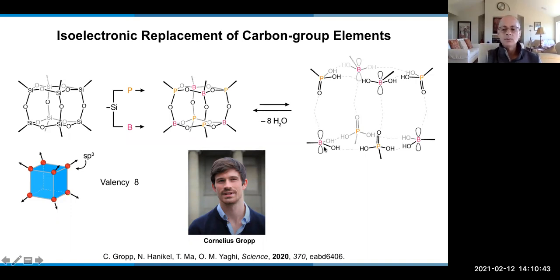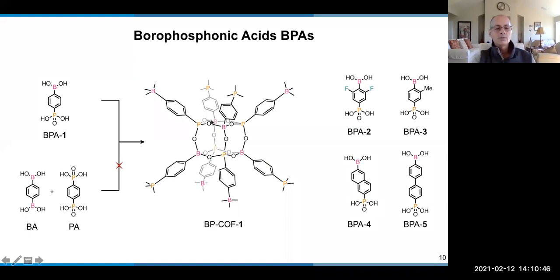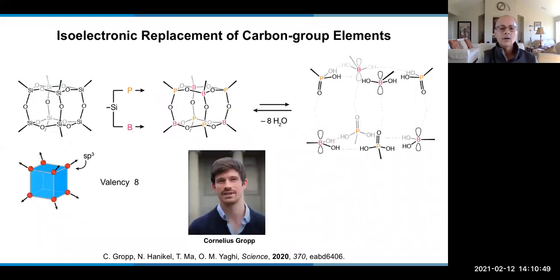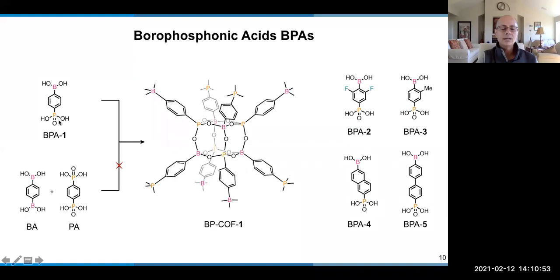So we thought this would work, and indeed, a great postdoc in my group, Cornelius Gropp, actually this was his idea entirely. First, we tried copolymerizing the diboronic acid and the diphosphonate, but that didn't work. What worked is that you make a molecule that contains the boron and the phosphorus. And because these are complementary, they come together into the cubic form. Now, there are molecular clusters known like this. And so we are following that kind of chemistry, except now we are successfully extending this into 3 dimensions.